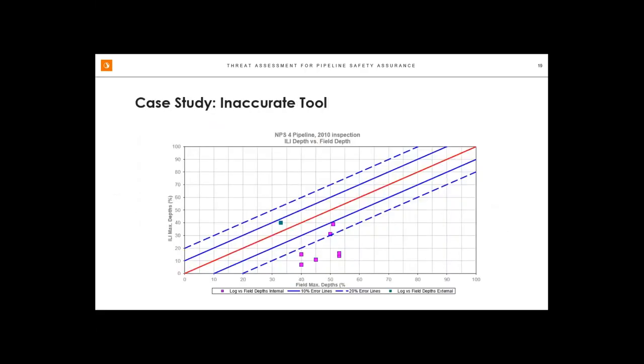And here's a good example of, again, what the QAQC process can yield. This was a pipeline that we were asked to assess in 2012. It had been inspected with an MFL tool in 2010. This was a small diameter line. It was low pressure, so there wasn't much concern about metal loss rupture. It was mostly leaks that were the concern. The ILI data, when we initially looked at it, looked fairly benign. Almost all the features were less than 30% deep, with a mix of internal and external corrosion. So not something that looked particularly exciting on first glance.